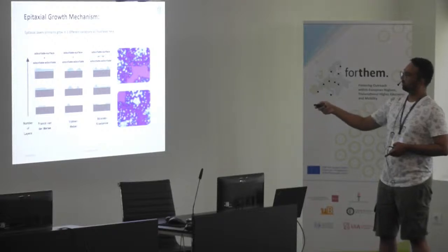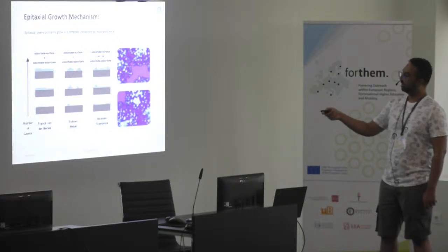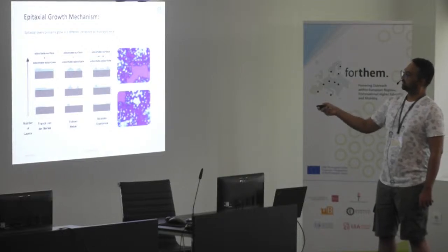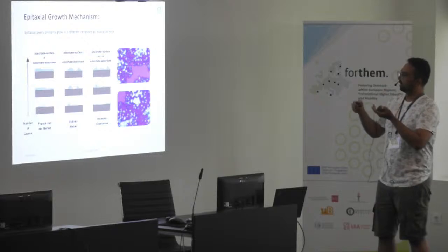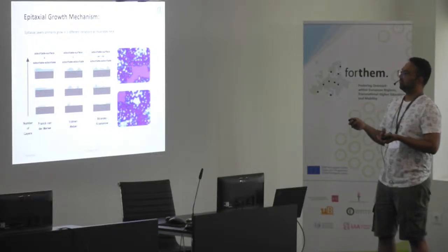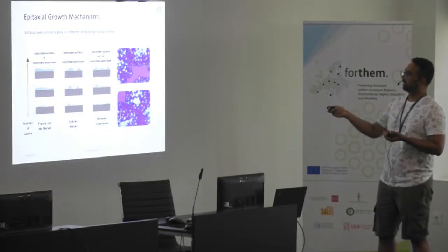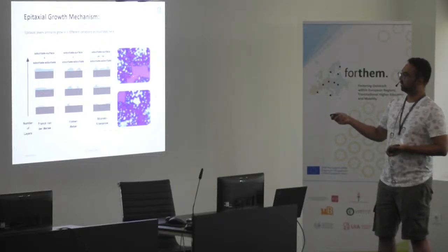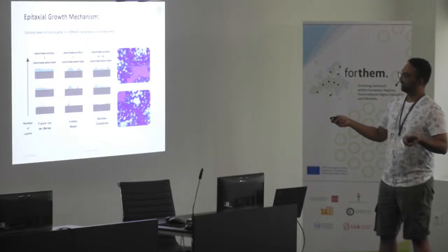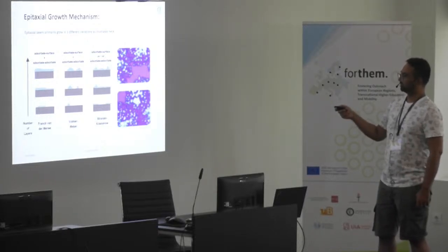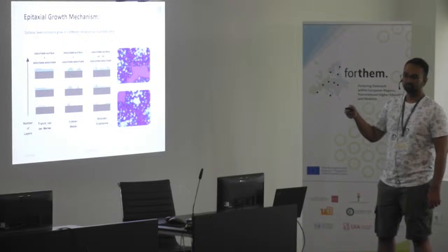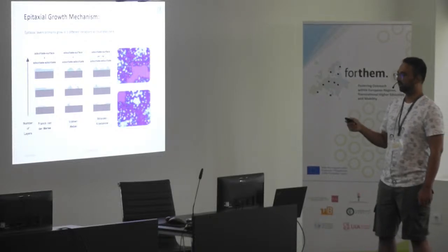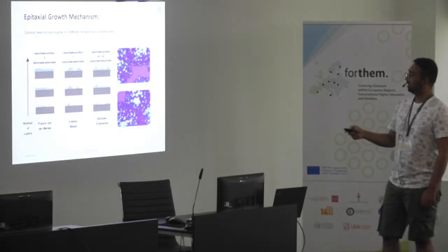So here we have the problem in the middle, it's called Volmer-Weber. The absorbent surface, the silicon oxide, has less attraction for the tungsten diselenide to grow than tungsten diselenide itself. So this is not the ideal situation, but it happens much more in real life. So in real life, we have many more problems.